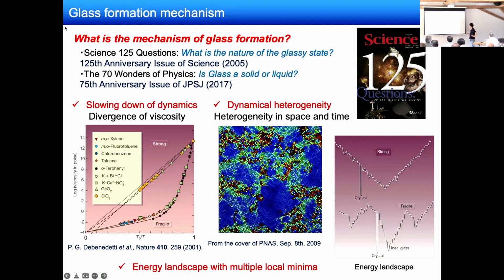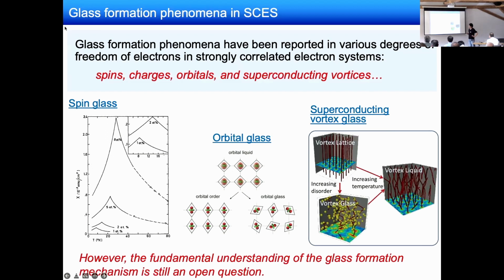And these phenomena can be understood in terms of the energy landscape, as shown here, where a number of local minima corresponding to metastable states, as well as crystal states, coexist. In this situation, when the liquid is cooled fast enough, the system can be trapped within a metastable state, and the system transforms into a glassy state. So this is the notion of the energy landscape for glass formation. And very interestingly, in strongly correlated electron systems, a wide variety of glass formation phenomena has been observed in various degrees of freedom of electrons, such as spin glasses, orbital glasses, and superconducting vortex glasses. However, the fundamental understanding of the glass formation mechanism is still an open question.